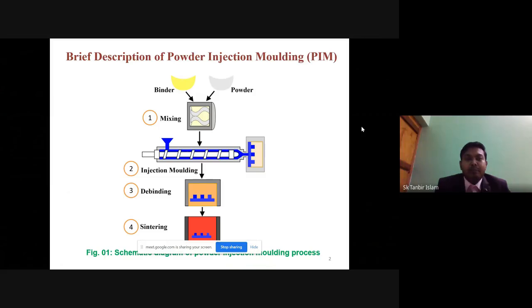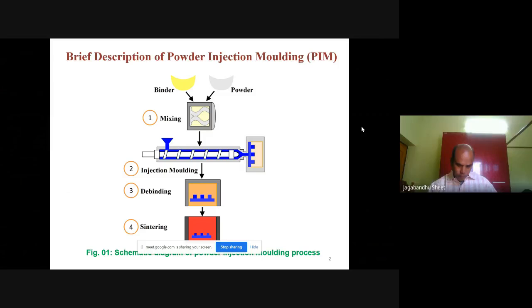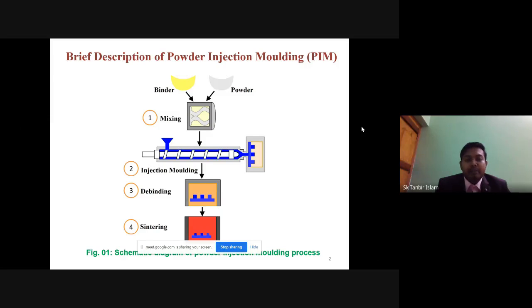For a brief description of powder injection molding, we can see here a schematic diagram, and there are 4 stages. First one is mixing, second is injection, third is debinding, and fourth is sintering. At first, in the mixing stage, powder and binders are mixed together. Then that mixture is called feedstock, and the feedstock is fed into the injection molding machine to give it a shape. Then that compact is sent for debinding, where the binder is removed from the compact, and then it goes to the sintering process, where particles are joined to give strength to the component. And micro powder injection molding is just like this, a miniaturized form of conventional powder injection molding.